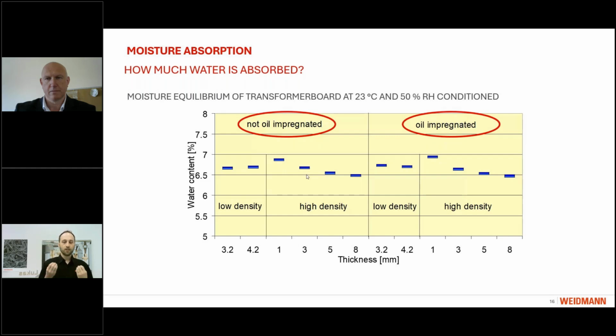What is very nice to be aware of with this graphic is that the oil impregnated sample and the non-oil impregnated sample reach the same water content. This means the water must be able to go into places where no oil is and where oil will never be. Because if there would already be oil, then the water could not go there. And so this really shows us that the oil and the water go into the material, yes, but with different processes and to different locations. This is important for you to remember. When we give enough time for the equilibrium condition, we always reach, at similar ambient conditions, a similar water content.